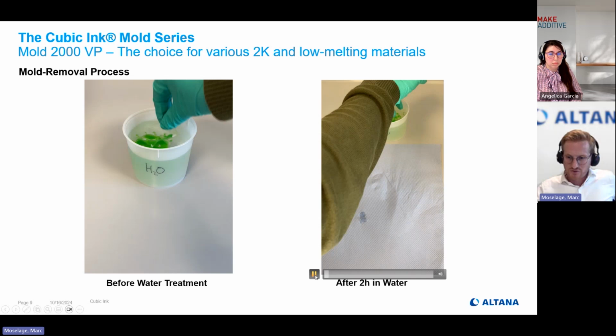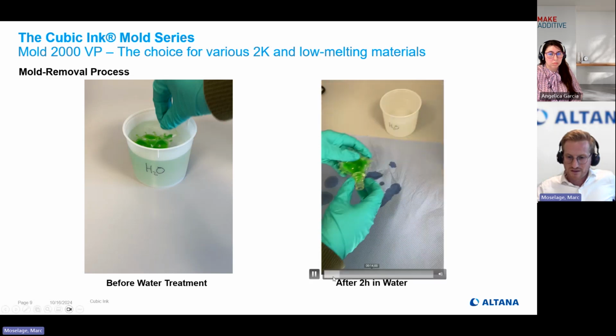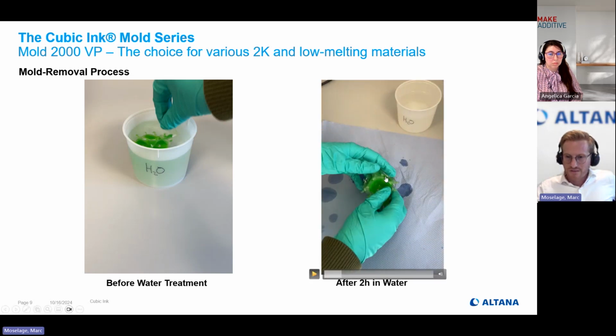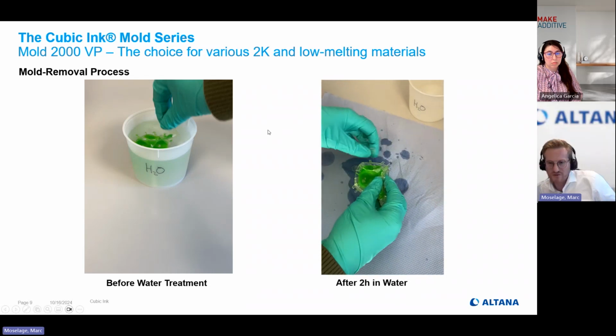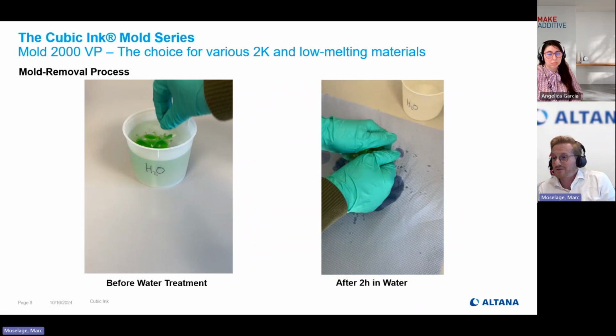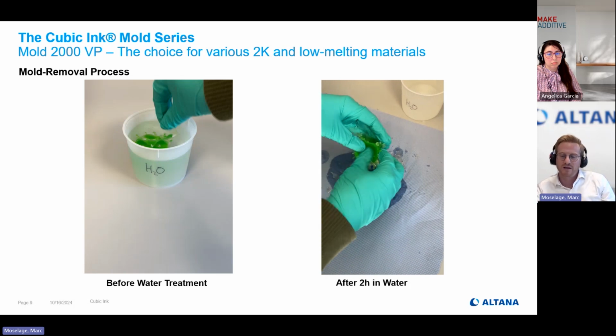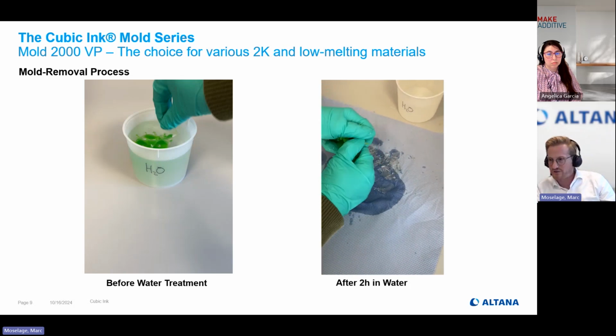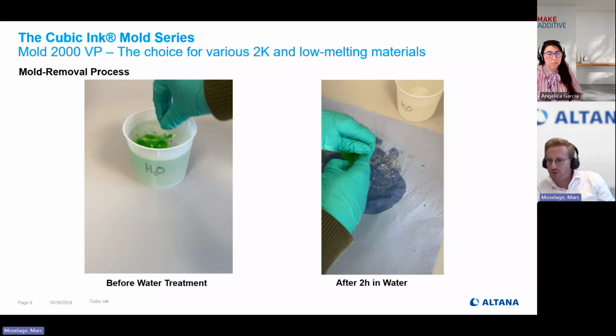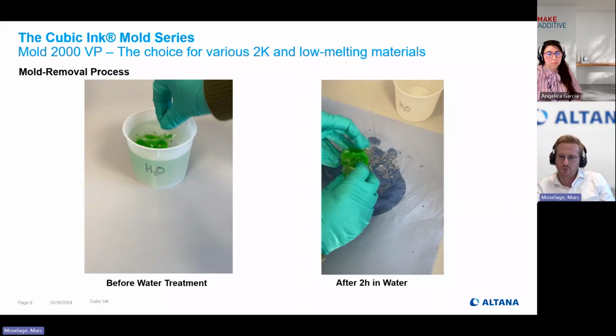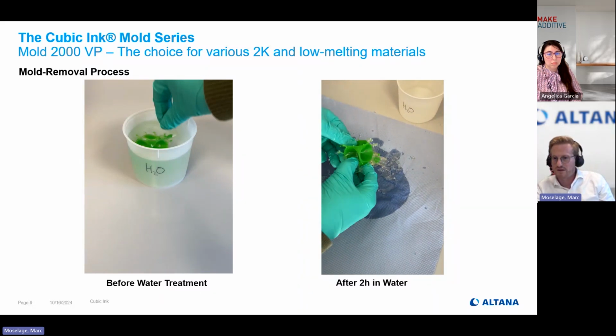So just by putting it out, you see already that the material, just by being in the water, has already cracked a certain bit. It loses basically all its rigidity, cracked to a certain point, and 2 hours in cold water is relatively short and not special conditions. And moving ahead, it's pretty easy to remove it. Since silicone is flexible, you need to stretch it one time, and then as you see here, it's pretty easy for this, let's say, easy to medium complicated geometry to fully remove the mold from the silicone.